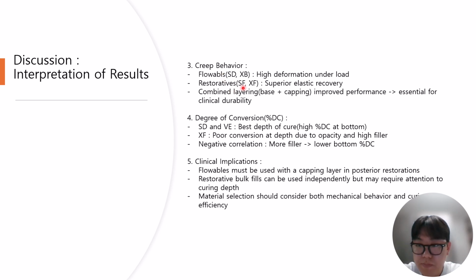Third, creep behavior. Flowables like SDR and Extra Base showed large deformation under load and poor recovery. On the other hand, restorative materials like Sonic Fill and Extra Fill showed better elastic recovery. Using a flowable base with a capping layer significantly improved creep resistance, which is essential for long-term clinical durability.